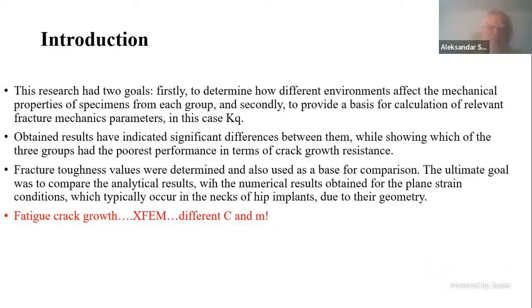So we decided to go on with KQ as a relative measure for these three states, and to use it to evaluate critical crack length. That would not be in the plane strain condition, but still it would be a kind of real condition, more or less. Then again, the other differences for these three states would be in Paris coefficients. So C and M were also evaluated by testing in three different chambers.